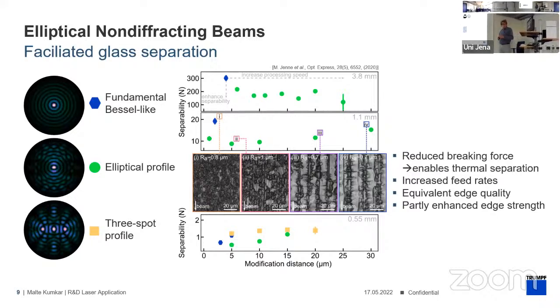Felix, you have some samples with you. So the upper one is for 3.8 millimeter in thickness. In order to separate them, 300 Newton are necessary for fundamental mode with a modification distance in the range of 3 micron. And in case you increase it by far, you can't break, or it will not be directed by the modifications anymore. But by using an elliptical beam, you can separate them more and more, and you can then easily separate them. And this works for thin materials too.